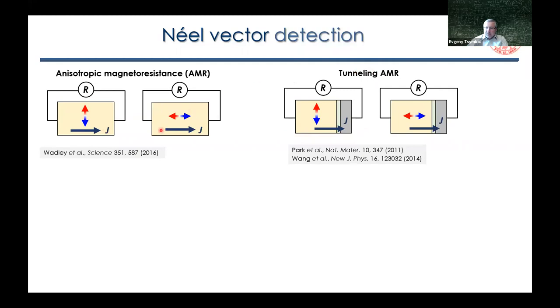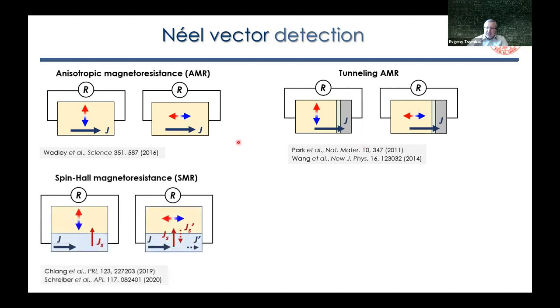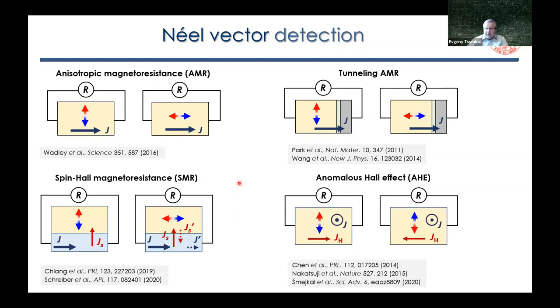So similarly, a similar effect can be observed using tunneling effect, where you have a thin layer separating antiferromagnet and an additional magnetic layer. Also, it was shown that quite efficient in detecting the Néel vector is an effect which is known as spin-Hall magnetoresistance effect, or SMR effect. So here, the current in the metal is dependent on Néel vector orientation through inverse spin-Hall effect, which provides some additional component to the current across the interface. This contribution depends on the Néel vector orientation. So finally, anomalous Hall effect was found to be very efficient in detecting the Néel vector.